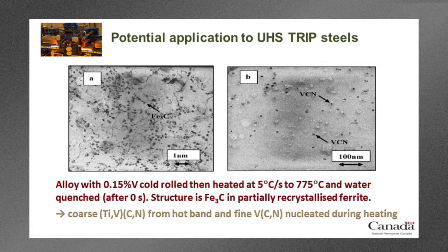On the right-hand image, if you look around about those cementite precipitates, we can actually see some very small vanadium carbonitride precipitates, and there are some rather coarse titanium vanadium carbonitride precipitates. The titanium precipitates would come out in the hot band, and the finer vanadium carbonitride precipitates actually mostly precipitated during this heating cycle after cold rolling.